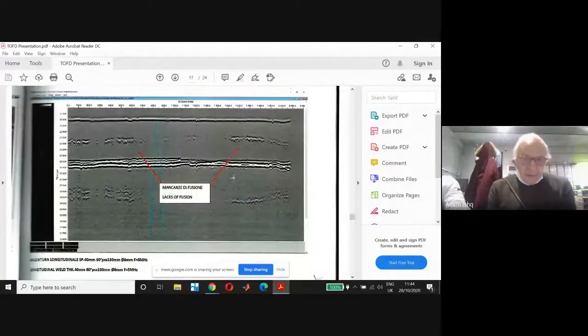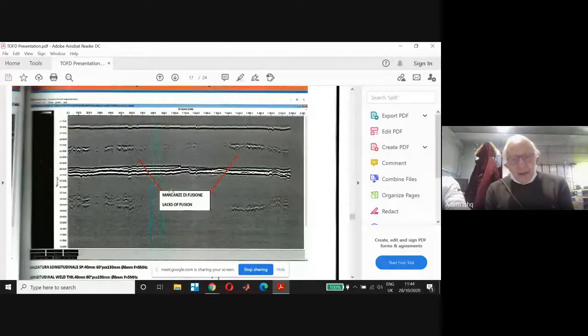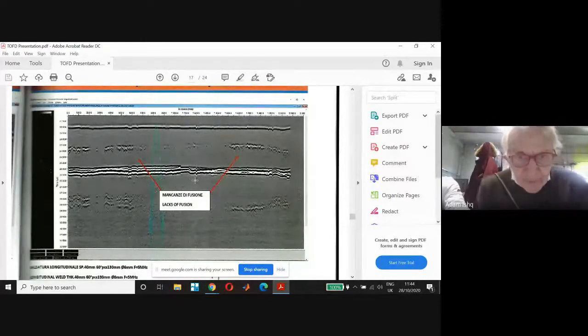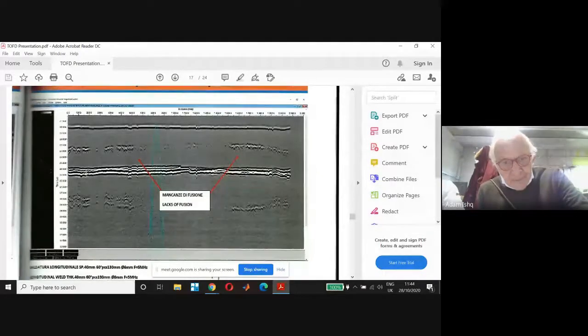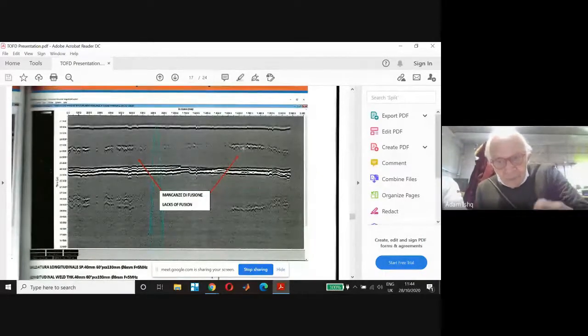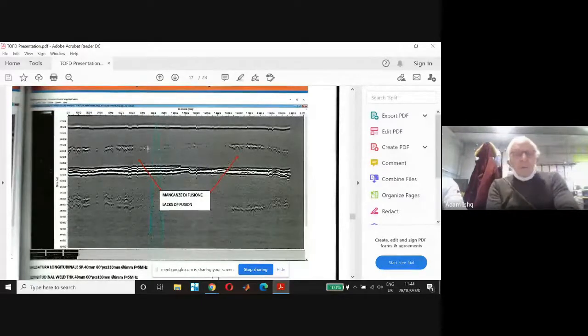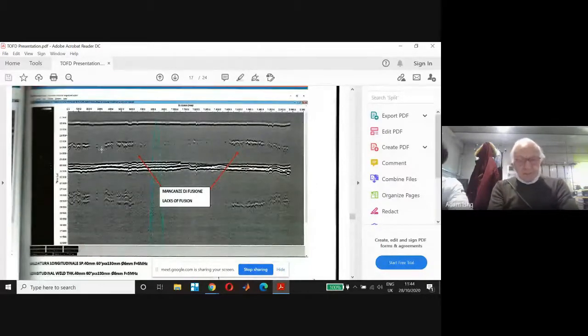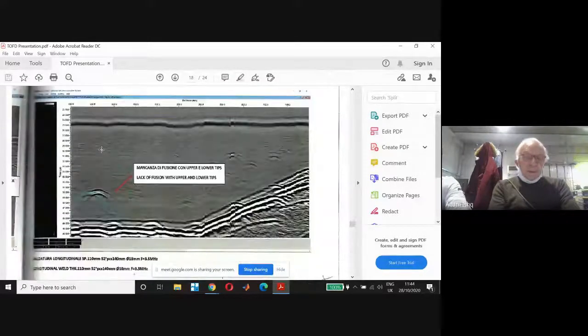Okay, here you see. Now you are professor because I ask you, where is the defect? And you say, oh, my friend, I see very well. The defect is in the center. That means here you have a smaller thickness and you have lack of fusion. You see a very long indication. So with time of flight, you can see as in radiography, but much better because time of flight shows you all the indications. With radiography, you cannot see all indications. Next picture. This is a reference book.